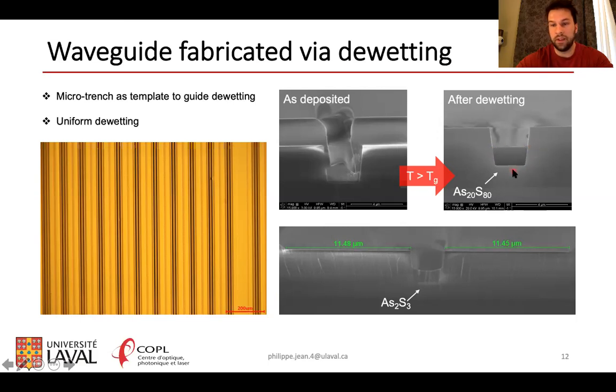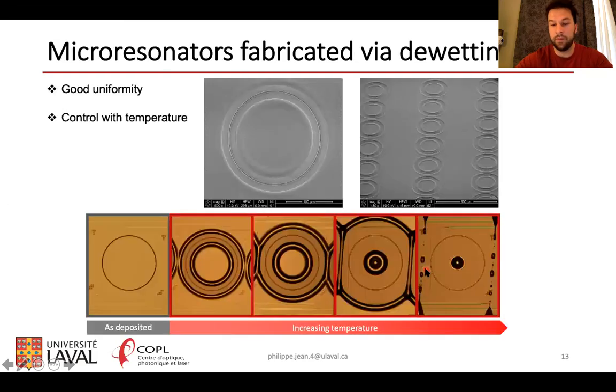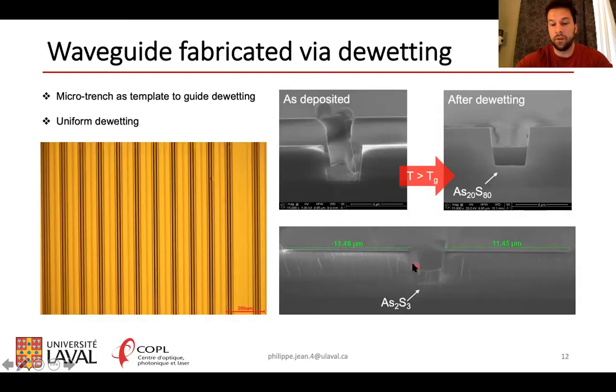This is with As20S80, and we can look here at a similar picture with As2S3, where again the rim is retracted almost outside of the picture. And if we look at the waveguide core, it's a pretty nice strip waveguide. But here you still have a bit of curvature in the top. This indicates that the As2S3 actually dewets less easily, let's say, than As20S80. What's interesting is if we look at this picture, we can see that over a relatively large area, dewetting creates very uniform shapes, which is very good.